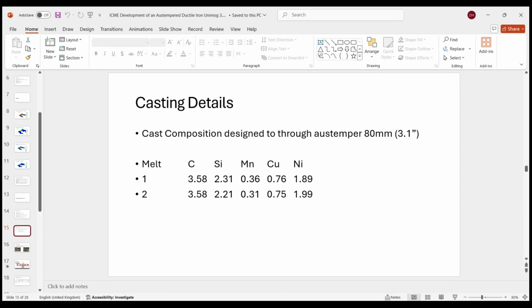For those of you who don't know ADI, we actually have to alloy the material depending on the section of the casting, because the heat treatment involves a very fast quench into a molten salt. I could talk a long time about ADI itself, but I'll keep it brief. Because it involves a quench into a molten salt, we have to add alloying elements to increase the hardenability factor. Now, we work with a hardenability factor of about 0.1 when we're doing our calculations.